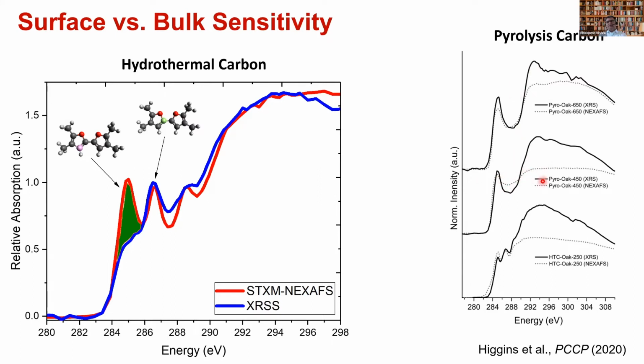So initially we were not sure if our spectra actually make sense, but there are a lot of systematic changes. As you can see at 450, the aromatic component on the surface and bulk is roughly the same. But that starts decreasing at higher temperature. Also, at HTC, you see that on the surface there's much more aromatic component than in the bulk. And a bit of this is also related to the way background is removed and so on. That is my best guess, but here it's mostly background, Jerry. I mean, you probably know better.